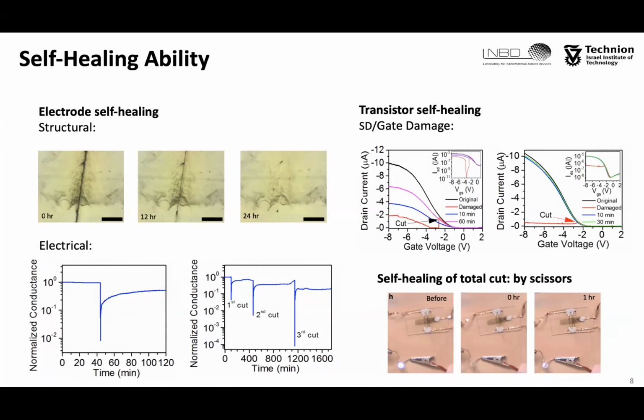Actually, it's 95%, and we have to wait another 23 hours in order to get to 99% recovery. In this case, the gate electrode could heal several cuts with negligible change in performance.